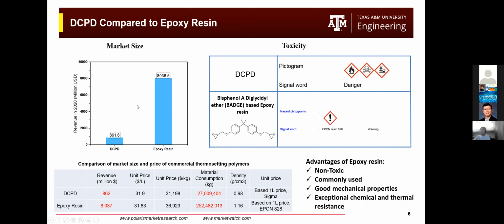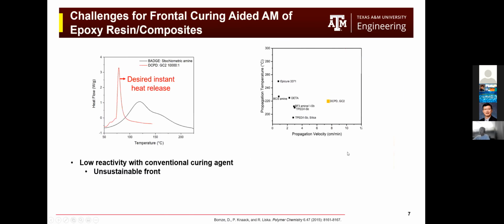One of the most significant restrictions for its application is, first, the existing market. The market size of this material is relatively small compared to epoxy resin, and also the dicyclopentadiene is very toxic in use, compared to epoxy resin, which is a good material to work with, non-toxic, and good in mechanical properties, and they also have a lot of other benefits in terms of their chemical resistance and thermal resistance properties. So then we're thinking maybe epoxy resin will have more impact if we can make it available for frontal curing using 3D printing technology.